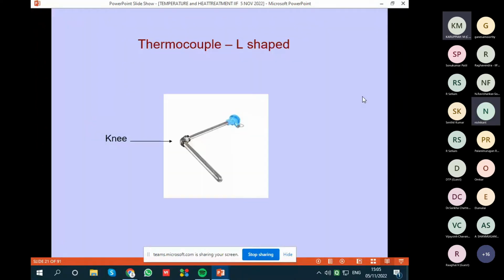In some processes, you use an L-shaped thermocouple. The interesting point is the knee, the bend. The bend is a very weak point in the thermocouple. Why weak? Because it gets hot continuously along with the tip. And if the knee is not properly protected or properly made by the supplier, the knee will open the thermocouple or short the thermocouple and give you a wrong temperature. So ensure that the knee is properly made by the supplier and does not give a problem. So the knee is very critical.